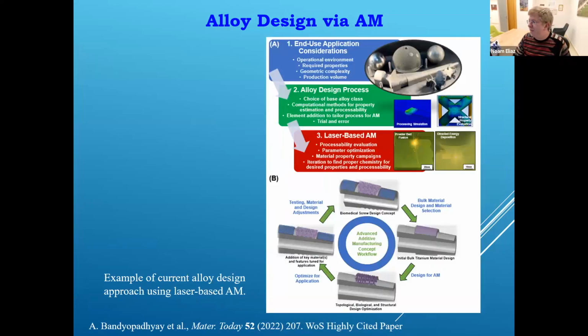Another application of DED is alloy design. It's a very powerful tool for alloy design. This is one of the reasons that I brought it to the university. You can combine machine learning algorithms, high-throughput design or computation tools with molecular dynamics as well, and then rapidly print a large batch of samples in one shot with modified chemistries or printing parameters, and then optimize the materials. Enrique Lavernia, for instance, has a very nice invention related to this with the development of new magnetic materials. We are now working on high entropy alloys in this case and some other materials.